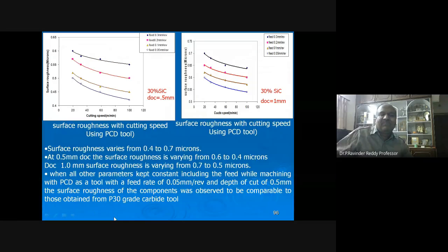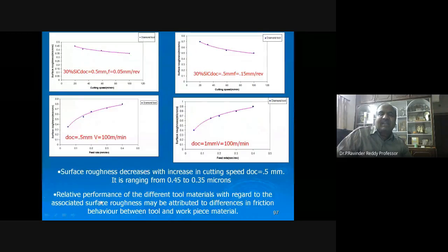So each tool we have conducted, even PCD you can have, with all the other parameters kept constant, including the feed. While machining with PCD as a tool with a feed rate of 0.05 mm per revolution and depth of cut 0.5 mm, the surface roughness of the components was observed to be comparable to those obtained from the P30 grade carbide tool. The relative performance of the different tool materials with regard to the associated surface roughness may be attributed to differences in friction behavior between the tool and the workpiece materials. So 30% with 0.5 mm, and then here 0.05 mm feed rate, and feed rate is increased, and here cutting speed is increased. Okay, so depth of cut is increased.